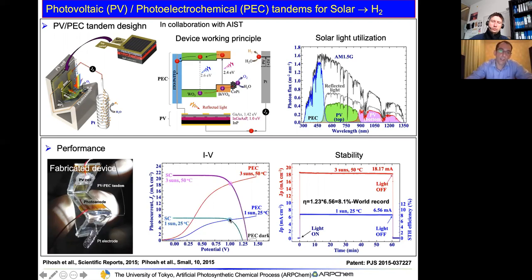The point where these two lines cross is actually the STH, the solar-to-hydrogen conversion efficiency. As you can see here, we realized 8.1% of STH, which is still a world record for that material. Actually, this work was published in 2015, so it's quite a long time ago.